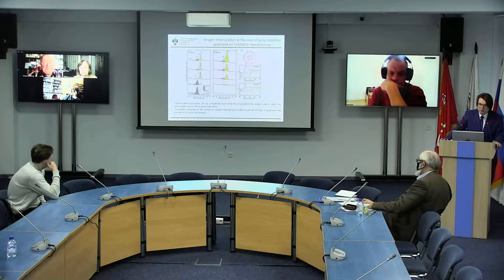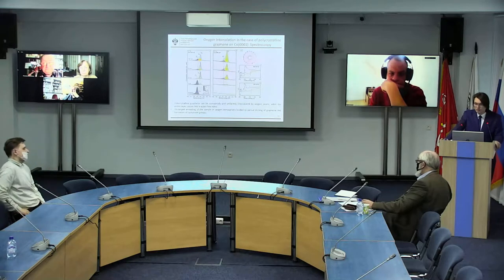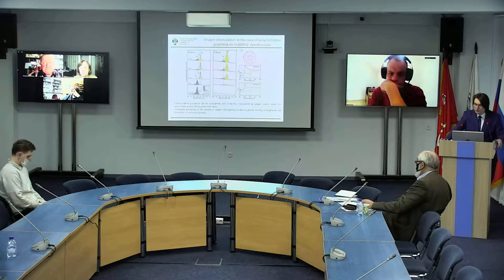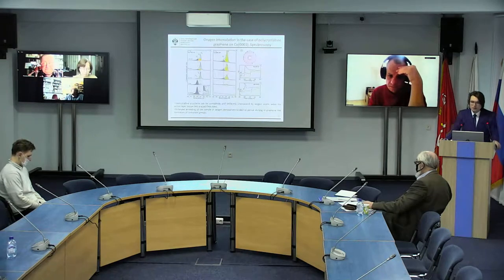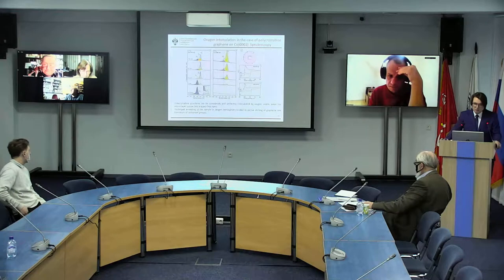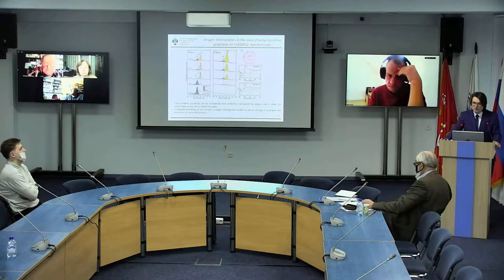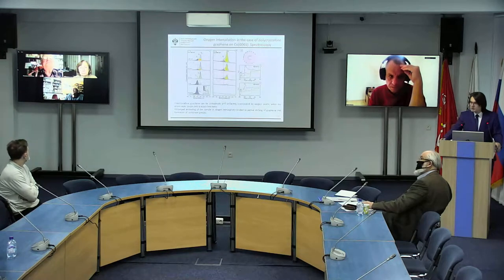And now let's shift to the last part of our study. This part is dedicated to oxygen intercalation of graphene on cobalt. Let's start with polycrystalline graphene on cobalt. We see that the heating of the sample of polycrystalline graphene in oxygen atmosphere leads to a rather quick and homogeneous intercalation of oxygen under polycrystalline graphene.